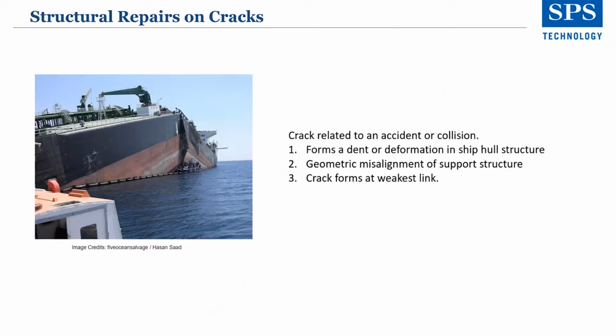Steel ship structures can develop cracks as a result of their all-welded construction or material imperfections, loading conditions, fatigue, and corrosion as they operate in highly corrosive environments. Welded ship structures are susceptible to damage during construction and operational life. Design inadequacies, material selection, material imperfections, improper welding, incorrect fabrication, or poor workmanship are some of the probable causes for damages during construction, while fatigue and corrosion are related to operations.